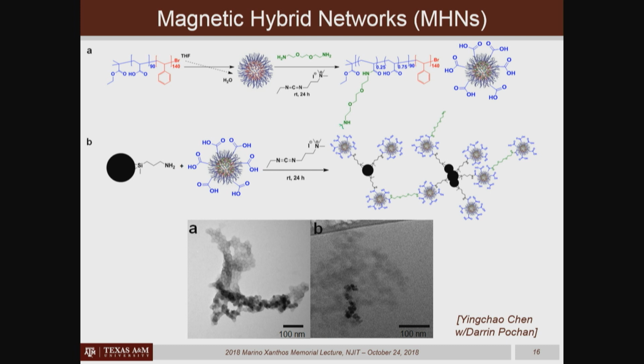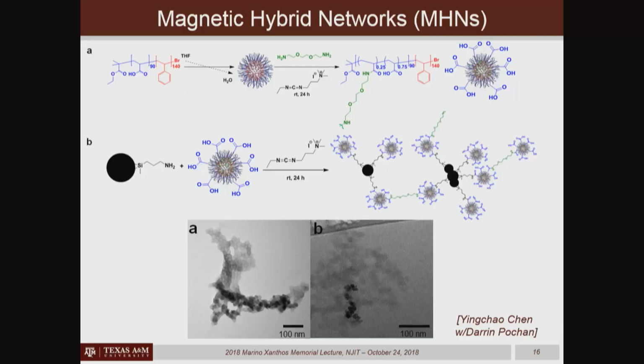And what she found was that in the first step, the cross-linking reaction involved the addition of a carbodiimide to activate carboxylic acids. And so if those activated carboxylic acids, they form these activated esters, encounter an amine, it forms an amide bond. If they don't encounter an amine, they get hydrolyzed, and the activated ester gets broken down. And so in the first stage of the reaction, the cross-linking occurred intramicellarly. But then when she had those cross-linked micelles and she added more carbodiimide in this second step, what she found was that some of these amide linkages that had formed might have a dangling amino group on them. So the shell of this particle isn't just presenting carboxylic acids, it's also presenting amines. And so that allows for coupling of one organic particle to another organic particle, because an amine from one particle can couple to a carboxylic acid on another one.